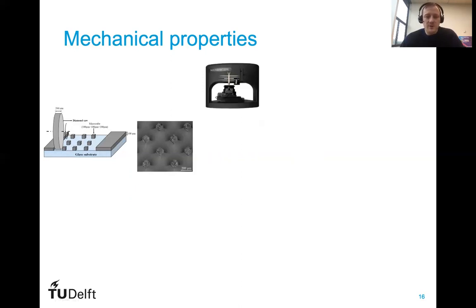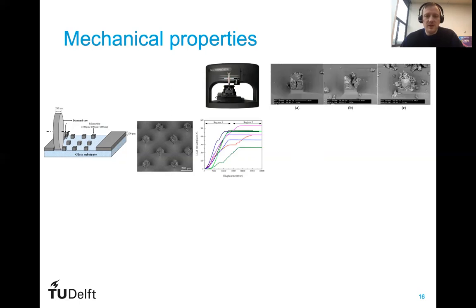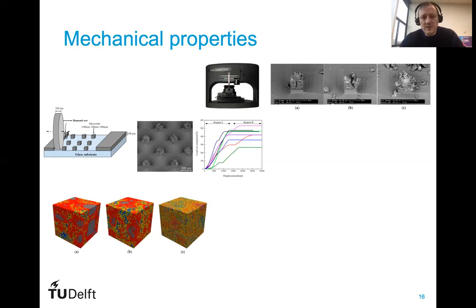And we can load them, we can measure the load and displacement, and measure the total force needed to break these specimens. So under a Berkovich indenter, this is what the fracture process of this small microcube looks like. And we get load displacement curves for these beams. Displacement in this regime is actually where the indenter catastrophically breaks the specimen, but the first part gives us the stiffness and the strength of these microcubes. However, this still doesn't give us properties of individual phases. So here we use numerical models to do inverse analysis and estimate the properties of different phases.